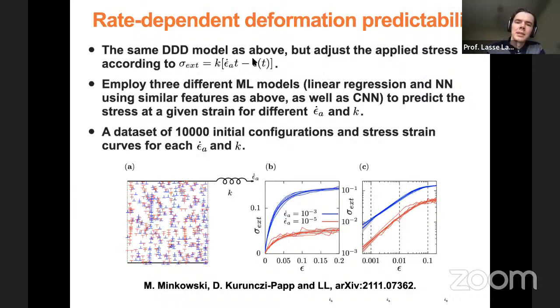To do that, we take the same model as above, but now instead of having a constant external stress, we adjust it according to this equation, where here is the strain rate with which you deform your sample, and this is the actual strain accumulated. And then there's some stiffness parameter K that relates to it. You can think of it like this: you have some kind of a spring with which you displace the top part of your sample. So you impose some shear deformation, but you drive it with a spring, so you have some finite stiffness.